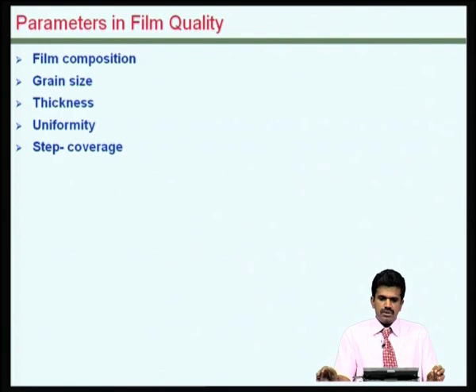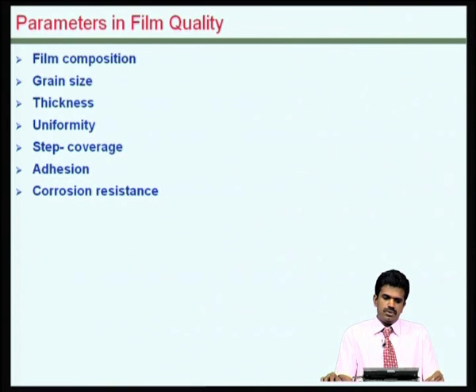pre-existing. So, in this case, when we transport materials from a source onto this surface, typically a line of sight rule is valid there, and hence the vertical edges of the structure may not get coated in most of the approaches. So, there are approaches such as rotating the wafer holder, or one needs to use non line of sight approaches for depositing films when a continuous coverage over stepped geometries is required. Adhesion is obviously critical in retaining structures attached onto the surface of the wafer. It is also important that the materials that we would choose are corrosion resistant, so that the performance is retained over a period of time.